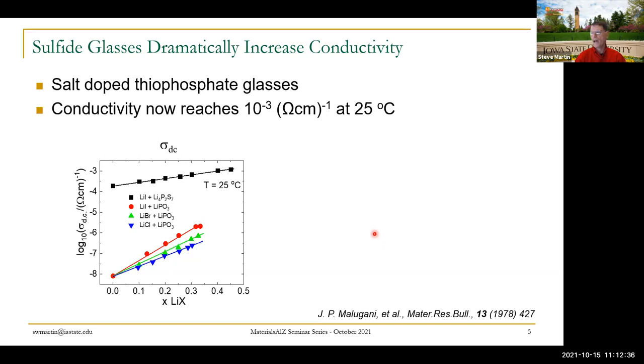for the conductivity. And this graph here shows some phosphate glasses, oxide glasses, and there's your low 10 to the minus eight or so. Basically the same composition, take all the oxygen out, replace it with sulfur, and you get conductivities at room temperature in this 10 to the minus three range. So at least one of the prime benchmarks of performance, ionic conductivity, can be achieved in these sulfide glasses. I'll talk about a lot more requirements in the coming moments, but at least that gets us into the realm of possibility for these compositions. That's a 10 to the 4, 10,000 fold increase in conductivity, which is the enabling conductivity that you need for lithium ion and lithium solid state batteries.